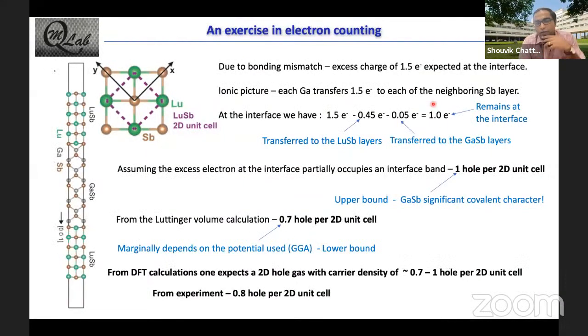So now we can also get a handle on the number of electrons that we expect by doing a simple exercise in electron counting. And here, let's assume that in the completely ionic picture at the interface, you would expect that the gallium transfers 1.5 electrons to each of the neighboring antimony atoms. Now, at this particular interface, as I told you, we expect that 0.45 electrons are transferred to the lutetium layer, and 0.05 are transferred to the gallium antimony layer. So the number of electrons you have remaining at the interface is about 1.